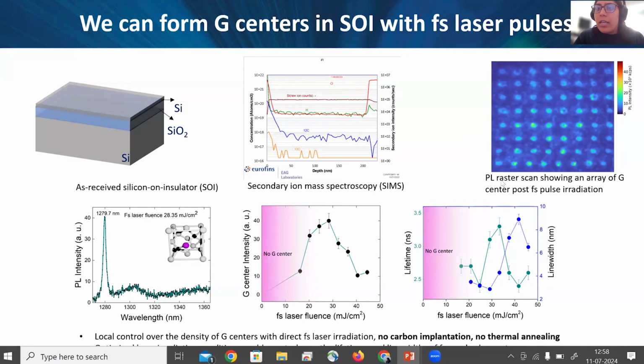So then we started out with this wafer and irradiated it with femtosecond lasers of different pulse energies. In the top right is the PL, photoluminescence, raster scan showing the different color centers formed by femtosecond irradiation of different pulse energies. Then if you zoom in on one of these spots, you have the spectrum, which for this case was related to the G center. Now if you change the laser intensities, you can fine tune the different properties. For example, you can change the density of the G center, and you can change the line width and the lifetimes. So this was a good proof of concept to check if a femtosecond laser can make any color centers at all.